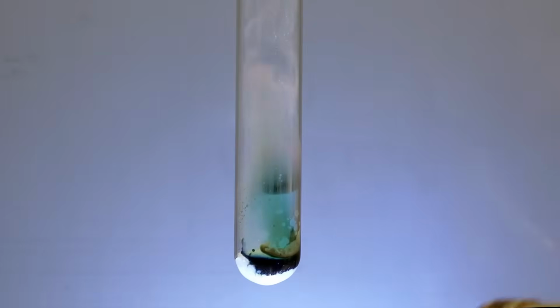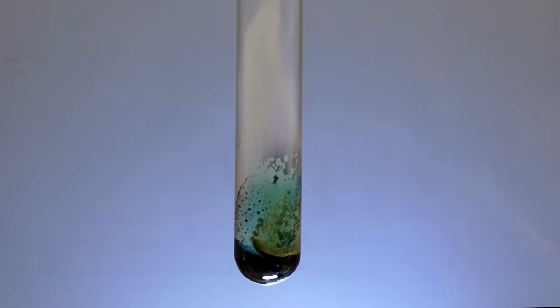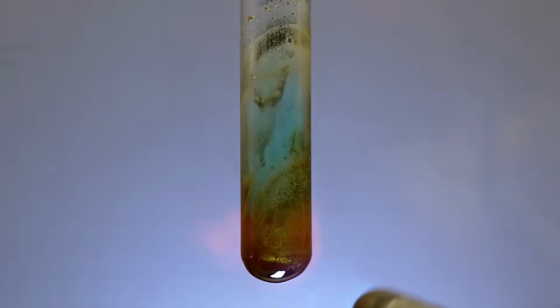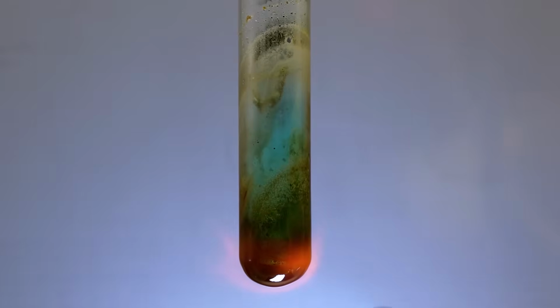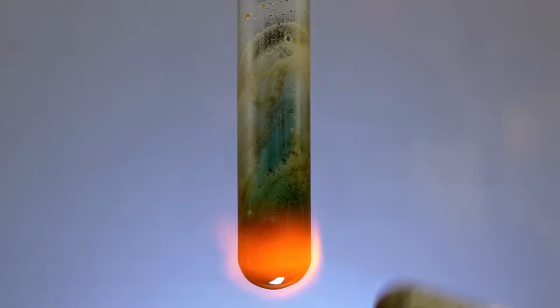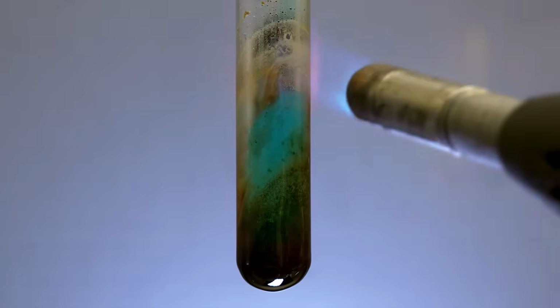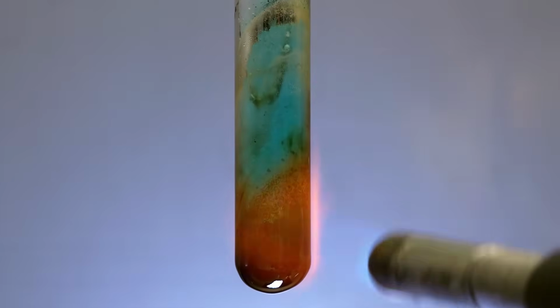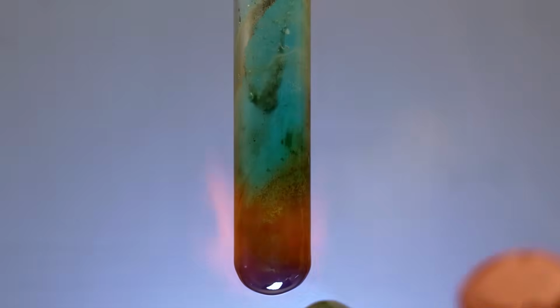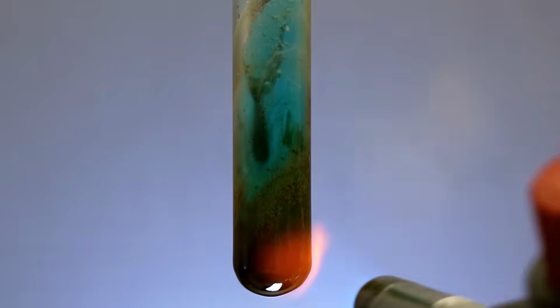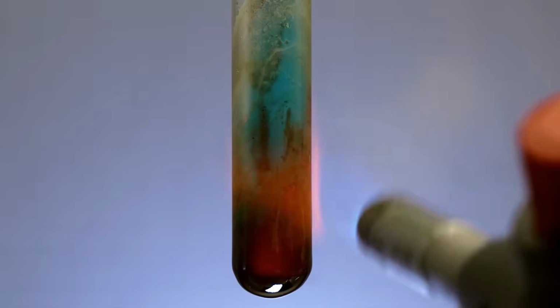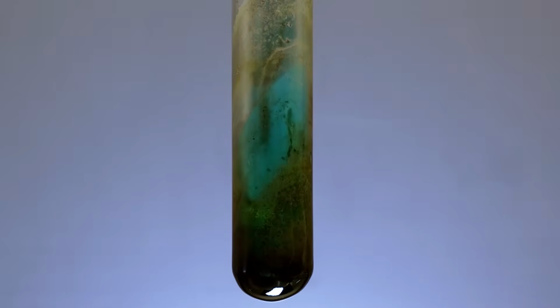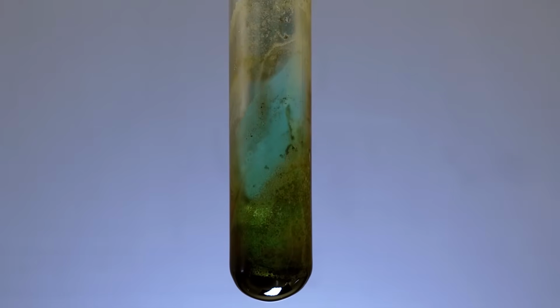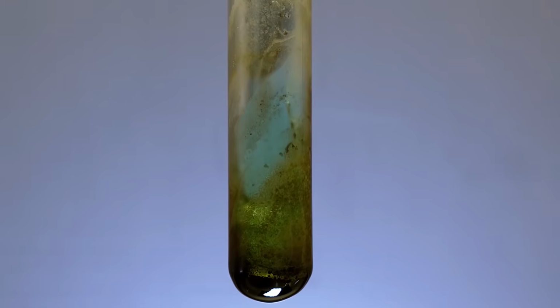In addition to the argon flow, the freshly produced nitrogen from the decomposition of potassium azide played a role, since it hardly reacts with potassium or its vapors. With further heating, the green color of the potassium vapor took on a bluish tint, and when cooled, the vapor seemed to become slightly yellowish, which surprised me. I think this strange color change of metallic vapor can be linked to electron energy, which changes with temperature. Because of this, at different temperatures, metallic vapor atoms absorb different spectra of light. But maybe some of you know a better explanation. Write about it in the comments.